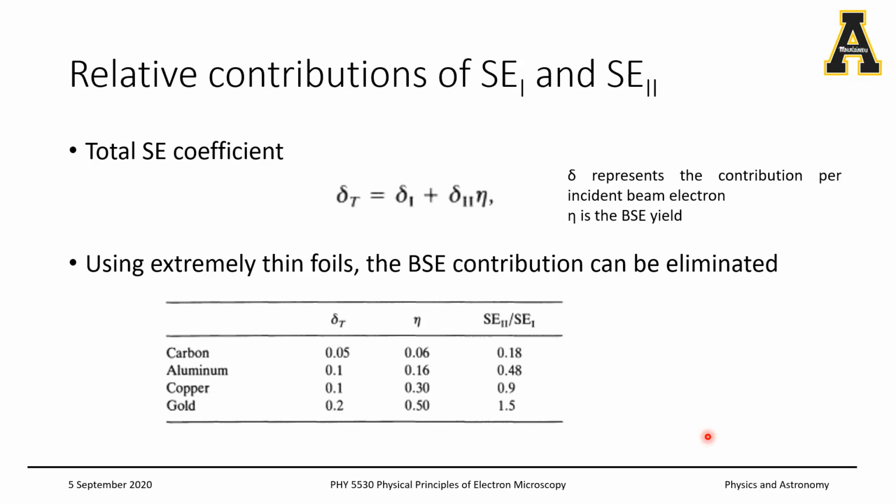So now you know that there are at least two kinds of secondary electrons. There are more, the secondary electron 3 and secondary electron 4. Those are generated due to inelastic scattering events occurring between the backscattered electrons that have made their way out of the specimen, along with the pole pieces and the other components in the electron column. I spoke about that in the previous video lectures, so please do correlate that with this, because it seems like by fragmenting the lectures sometimes there's a loss of continuity. But either way, we are going to focus on SE1 and SE2. These are the ones that are generated from the incident beam and the backscattered electrons while they were going out of the specimen.